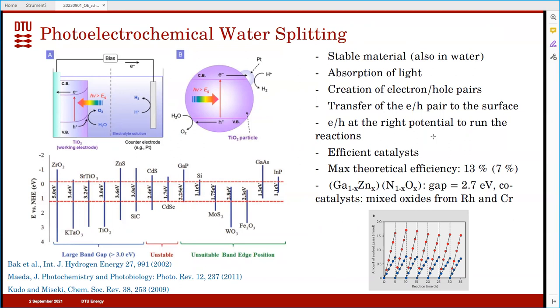And there are a bunch of materials here that could do the trick, but some of them have a very large band gap, so above 3 basically. You know the solar spectrum, where the high intensity is at about 1.3; above 3 you have 2% efficiency, so forget about that. Then some materials are good to run only one of the two reactions. For example, silicon could run the hydrogen evolution, but not the oxygen evolution. Molybdenum disulfide does the opposite.